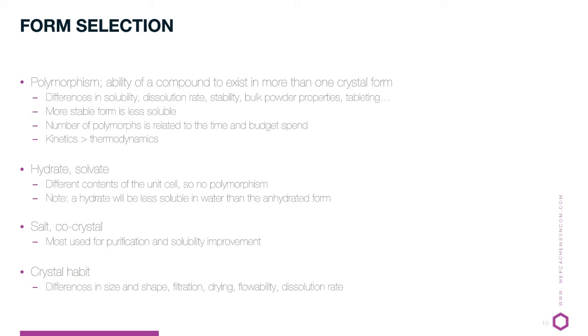Next, when you look at the crystal habit, there are differences in your crystal size and crystal shape, independent of whether it is the same polymorphic form or a different form. That will give you a different filtration rate, different drying properties, different flowability, and in the end also a different dissolution rate. So to improve your dissolution rate, you can go to a smaller particle by micronization. Or to improve the drying properties, you can go to a larger crystal, with less surface, and therefore it will dry faster. Depending on the properties of the material, certain texture needs to be adjusted and optimized.